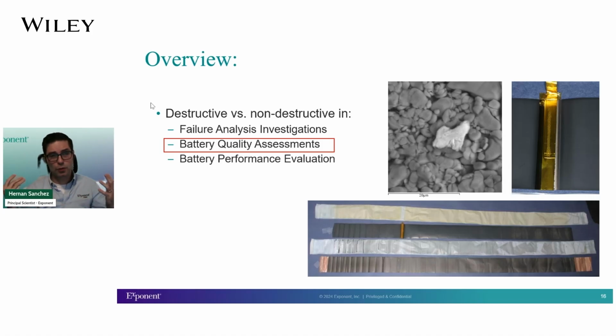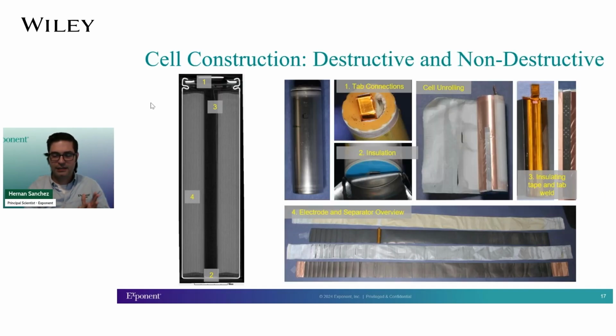Speaking of that, using the information from a failure investigation or just due diligence from a quality assessment, there's a lot of things that both the non-destructive and destructive techniques can teach you. Not to belabor the point that CT is a fantastic technique, and there's been a lot of advances on fast CT scanning of batteries, so you can get information about their alignment, how they look inside, and everything. But there are certain things that can be enhanced by complementing that with destructive testing. For example, getting a good sense of what your tab connectors look like, your insulation, what your tab welds look like, and particularly where the insulating tape sits on top, because those are things that are a little bit harder to detect purely with non-destructive techniques.